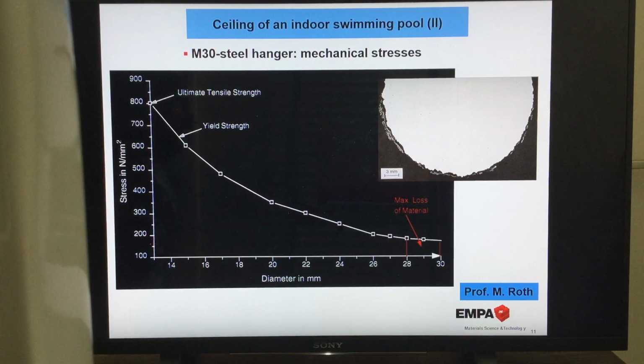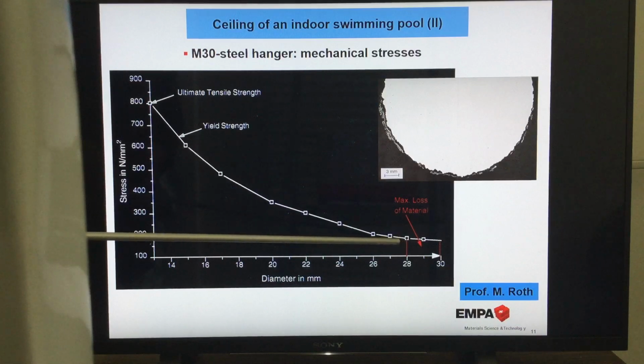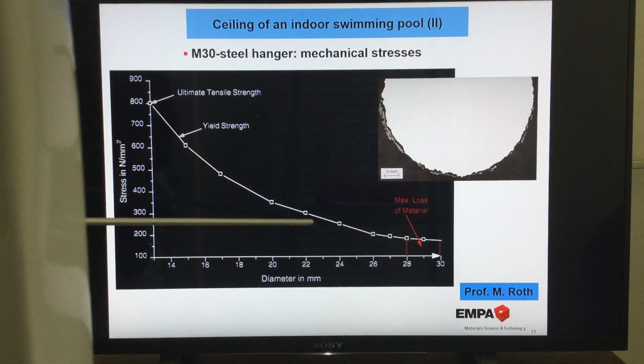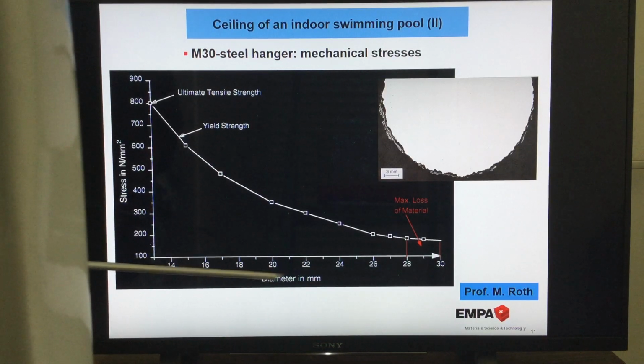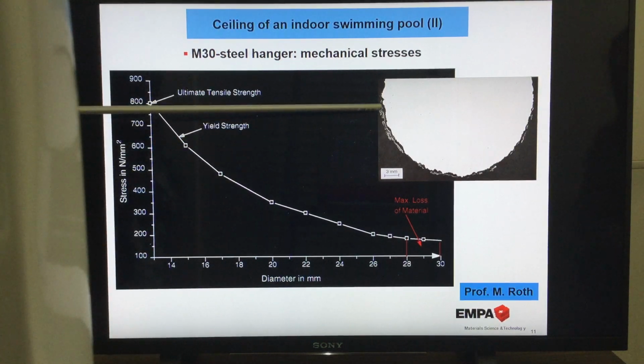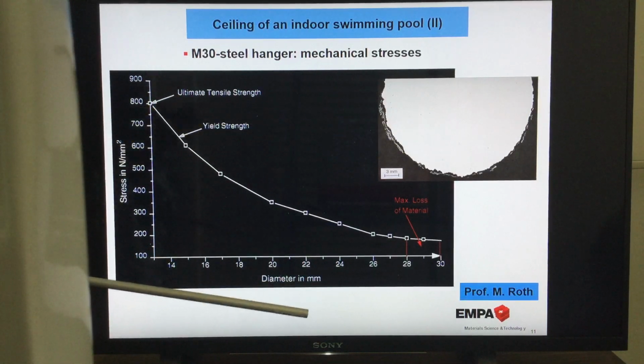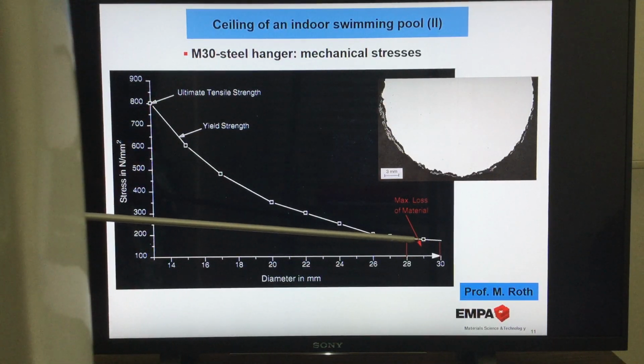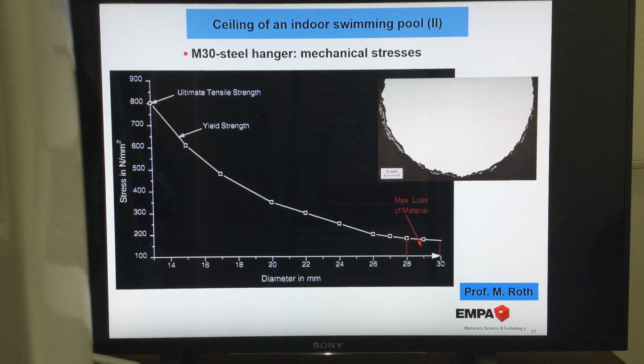Very far away. And due to the fact that it is so far away, you easily can calculate here because we have the diameter, we have the load on each steel hanger. I told you 11 tons. You can easily calculate then the stress, how it gets a little bit higher when there is less diameter available. Okay, look, when you come here, of course, when you have instead of 30, you have 18 millimeter diameter available, then the stress gets higher and higher. That's clear, it gets less. But in our case, where we have only a loss of about 2 millimeters, you can even say 3 millimeters, it's only a slight increase of the stress. So that seems to be quite safe, very safe.